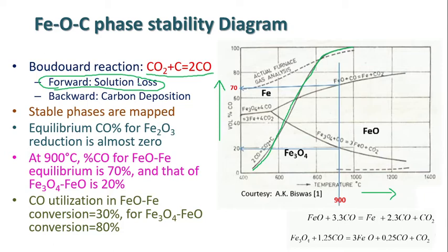This reaction is highly endothermic and has a very large activation energy for chemical kinetics. Therefore, it proceeds at an appropriate rate only at sufficiently high temperature. So, the temperature relationship tells that at higher temperature, the forward direction reaction is preferred.